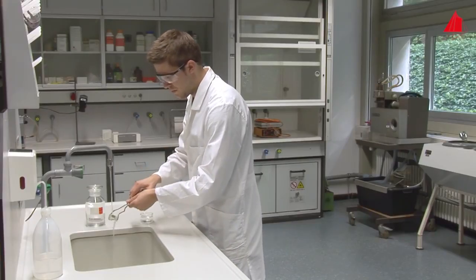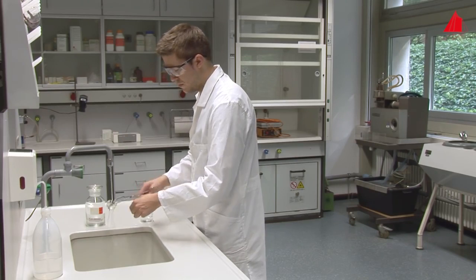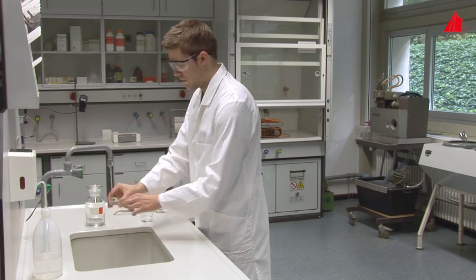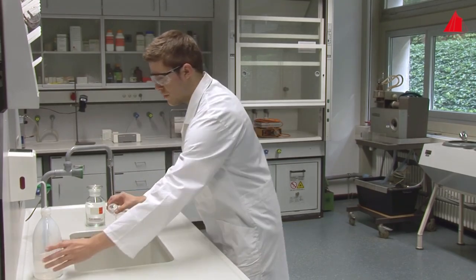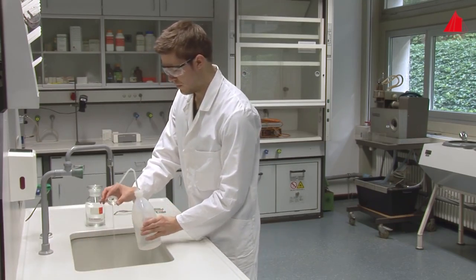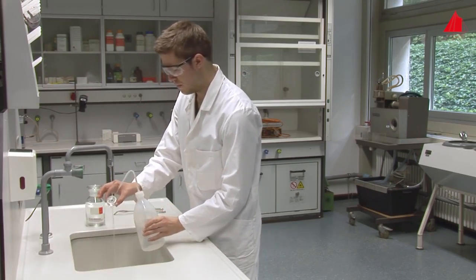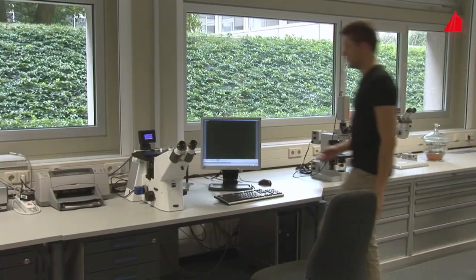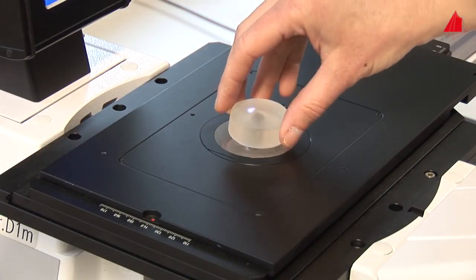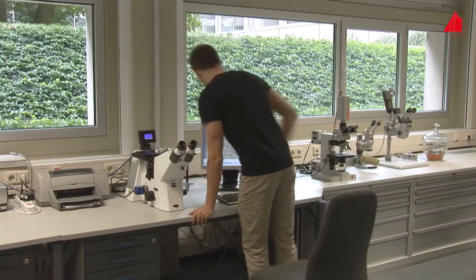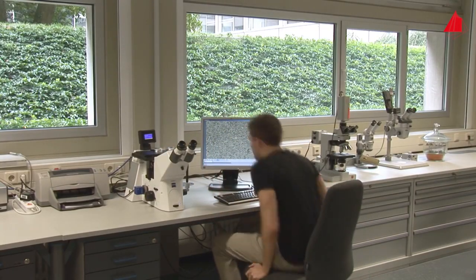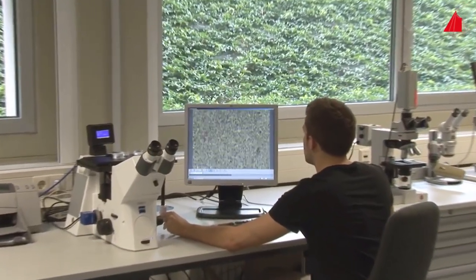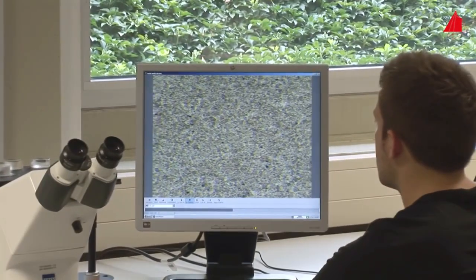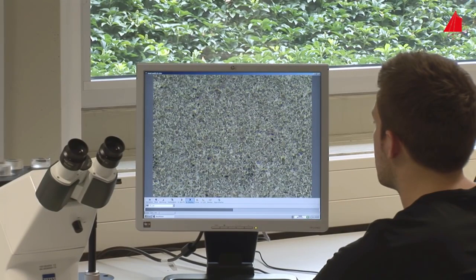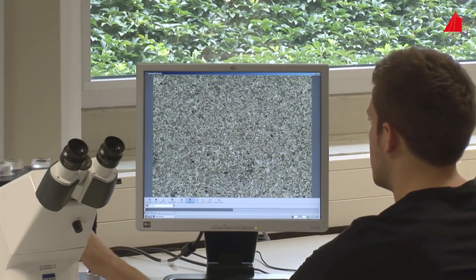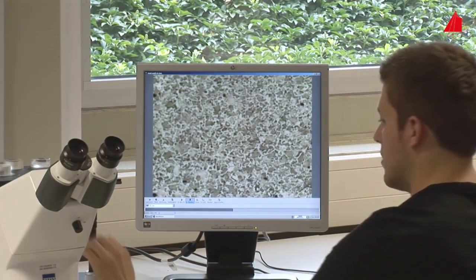Then he rinses the microsection thoroughly with water and afterwards with alcohol. The hairdryer is again used for drying. The excitement increases. Was the etching time correct? Has everything worked out fine? At low magnification, not much can be seen, which looks characteristic. The tester gradually switches over to higher magnification.